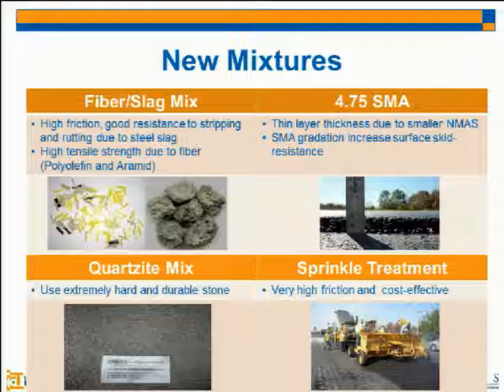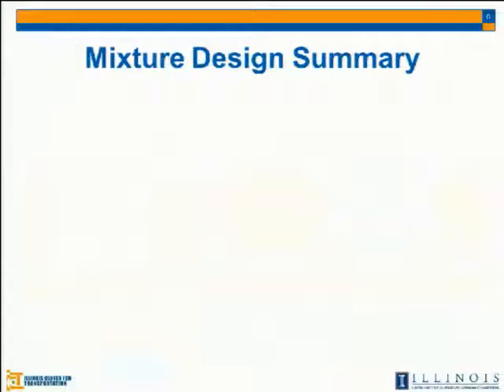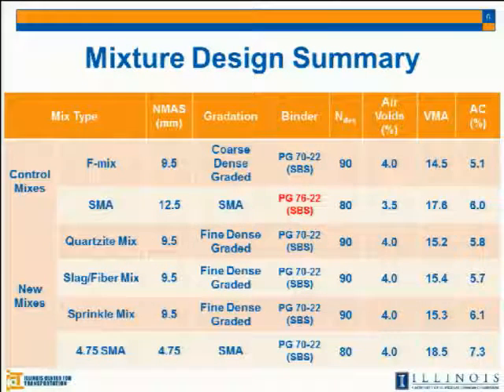But by using less expensive base materials, we can save money, but we can increase some friction performance. So here is the mix design summary for the six mixtures. We have a 12.5 SMA mixture and 4 9.5 dense graded mixes, but the control mix has the coarse dense grade, while our new three mixtures have fine dense graded mixes.